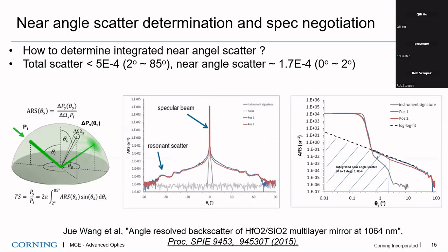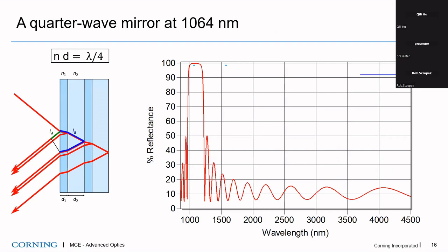We work with the Fraunhofer Institute in Germany, in Jena. That's another optical valley or center in Germany, similar to Rochester in the US. So we determine the angle resolved scatter. One challenge is that it's very challenging to determine the near angle scattering at less than 2 degrees from the specular beam. So what we did, through literature, using log scale on the right, we can predict the near angle scatter based on the angle resolved scatter measurement. And then from that, we share with our customer and convince them, basically to provide a manufacturable specification for us.